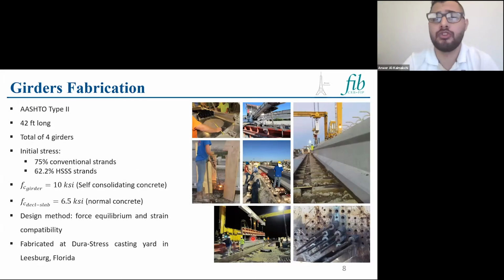For girder fabrication, we chose AASHTO Type II, 42 feet long. We had 4 girders. The initial stress for the conventional strand was 75%. We had to go lower than this value because of the ductility issue in those strands, so we tensioned the stainless steel strands to 62.2% of the ultimate. The specified strength for the girder was 10 KSI, and for the deck slab it was 6.5.